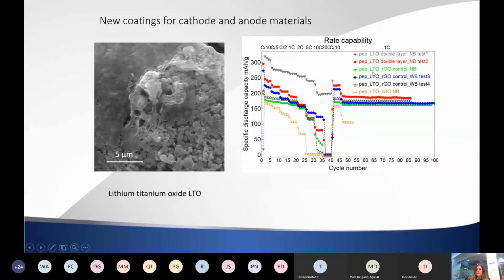And we could see that this green curve here is when we cycle the battery without any binder, trying to improve the interface with the anode, between the titanium oxide and the graphene. And this is when we use optimized peptide. So we can say that maybe the peptides are not, we are studying that, the best electronic transport molecules, but they improve the interface and they tie together the graphene to these lithium-based materials, and they can help to improve the capacity of the battery.